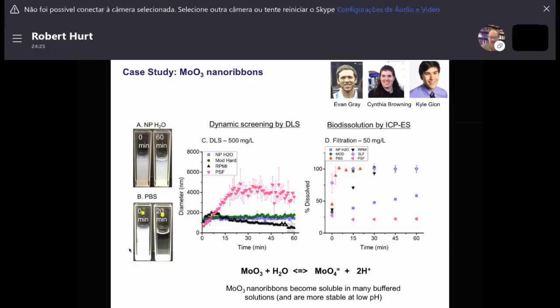And we eventually found out that the material was undergoing a basic hydrolytic dissolution process to produce molybdate, which is a soluble ion, and gives off protons. And in simple water solutions, those protons make the solution acidic, and the molybdenum reaches an equilibrium. So we have a stock solution with nanoribbons and some dissolved material. But if you look at conditions found in the body, conditions where the particles are ultra dilute and where there's buffers that maintain the pH at levels needed, say, for cell growth, under those conditions, these materials are very unstable.